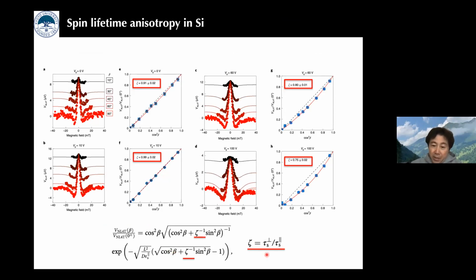As I mentioned, the existence of spin lifetime anisotropy is the fingerprint of the synthetic Rashba fields. So we measured the spin lifetime anisotropy in silicon by changing the gate voltages. As I show here, zeta is an anisotropy factor, and when zeta is equal to 1, spin lifetime is isotropic, the same. As you see, the value is quite close to 1 at low gate voltages, but when we apply a large gate voltage, the zeta value is almost 0.75, far from 1. This means a large spin lifetime anisotropy takes place under the strong positive gate electric field.